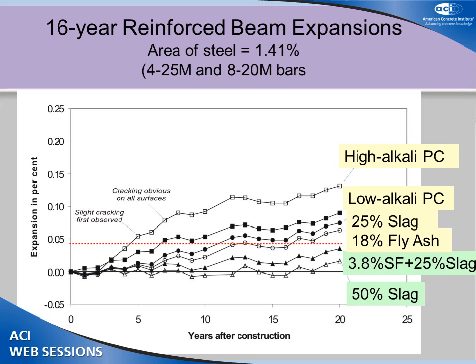Now the reinforced concrete beams, the expansions are lower. The restraint of the steel did restrain the expansions. So the maximum expansions, instead of being in the order of 0.23 at later ages of the high-alkali cement, you can see they're about 0.12. So it cut the expansions in half, having that restraint in the longitudinal direction. But again, the same ranking is there.